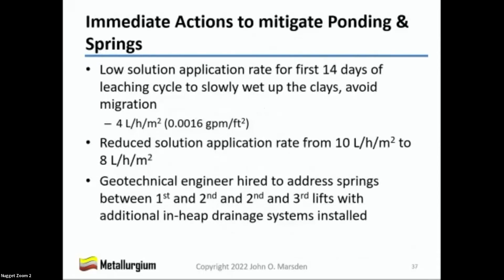He immediately issued instructions to the heap leach operators to run at a reduced solution application rate of 4 liters per hour per square meter for the first 14 days of the cycle. That allowed him to wet up all the clay material, the clay minerals slowly. And then he would ramp up to a target application rate of 8 liters per hour per square meter, a little bit lower than the original design.